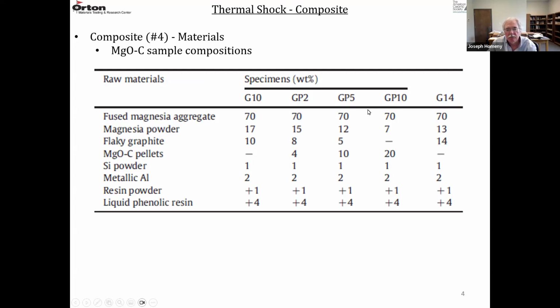So there were 5 compositions here. They all had 70% fused MgO. They all had about 1% silicon metal, 2% aluminum metal, and then the resin between the powder and the liquid portion was 5%. So what they varied was the magnesia fine powder, the flake graphite, and then the amount of these pellets they created.